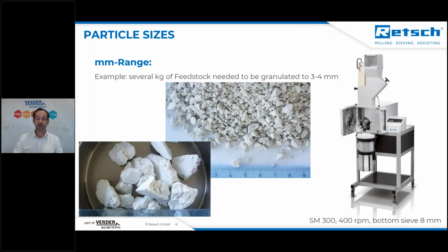But here the task was a bit more difficult, because for an injection molding or extrusion process, we need to grind the particles down to a few millimeters, but we had to avoid the generation of fine powders. And this is quite difficult because it's easy to grind smaller, but you always have got lots of fines in your sample.